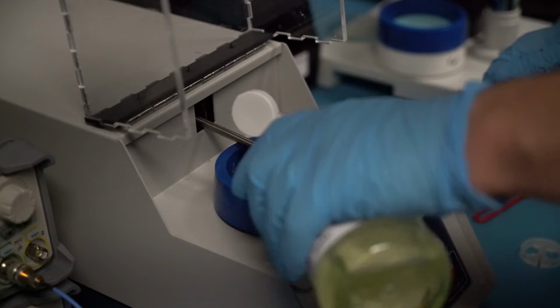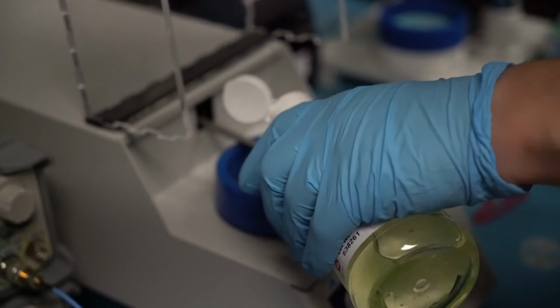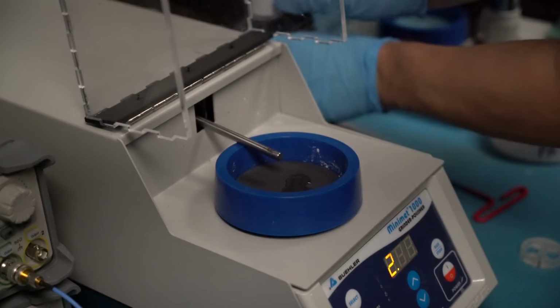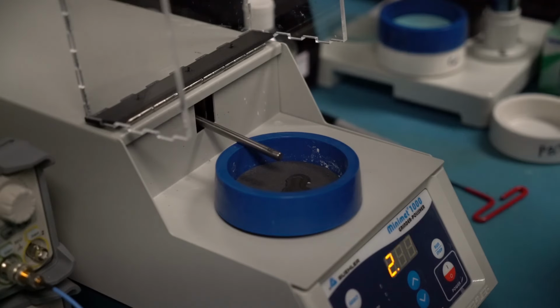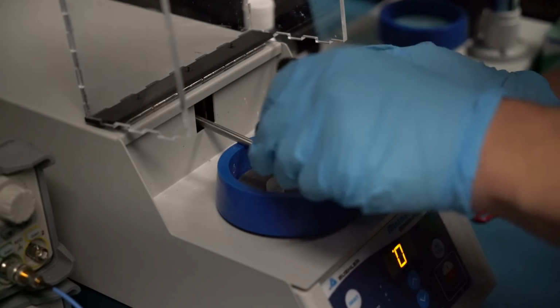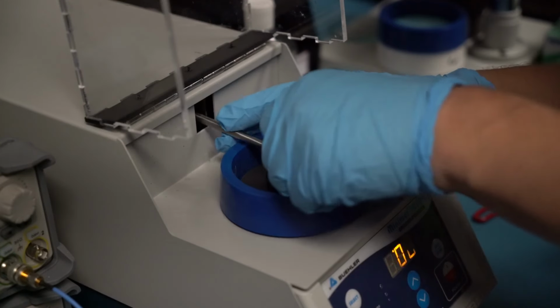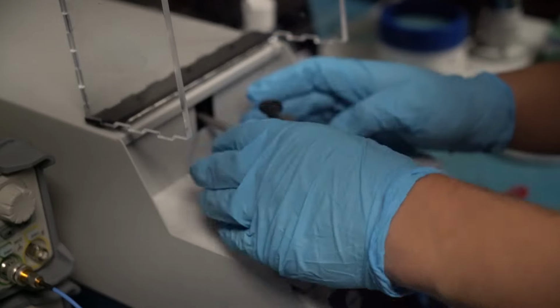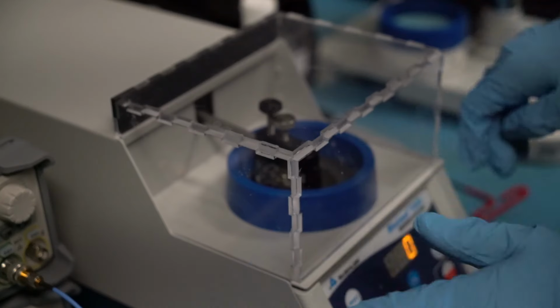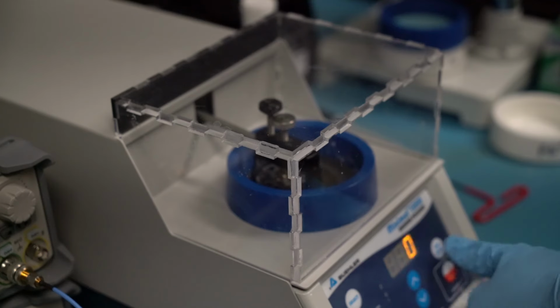The actual chip is about 4 millimeters thick, and the entire sample measures about 6, so we have approximately 2 millimeters of resin on the back side. Back onto the polisher, we're going to do pretty much the same thing on the front side, and the goal here is going to be to remove most of the 1 millimeter of package before we get to the silicon. We want to take off probably around 700 microns and then switch to finer abrasives as we get closer.